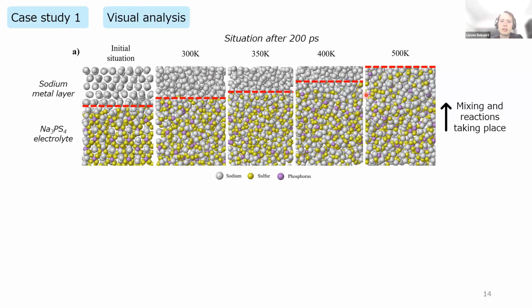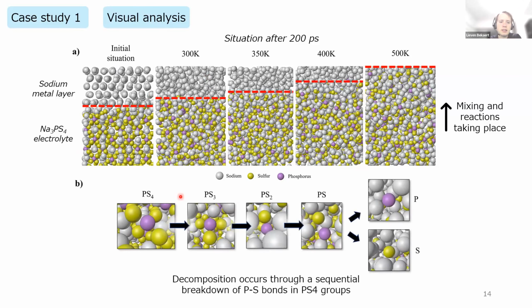So if we zoom in a bit, then we can see that what actually happens is that these PS4 groups, which are present in the solid state electrolyte, they break down upon reaction with sodium. So sodium gets in between those phosphorus-sulfur bonds and then breaks off sulfides, and you get PS3, PS2, PS, phosphide, and sulfide groups. But of course, visually, there's a lot of information, but atoms also have electrons, and so atoms have a property called charge.